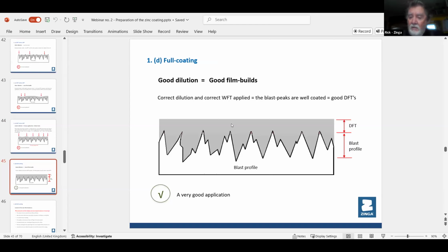It shows you the blast profile, and it's been filled with Zinga, and it shows the DFT above. So when you're measuring the wet film thickness, your little film gauge is actually sitting on top of the blast peaks, okay? So it's measuring from the top of the blast profile. That's where it should be.